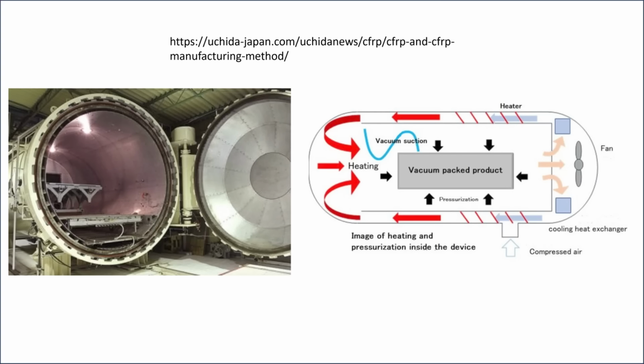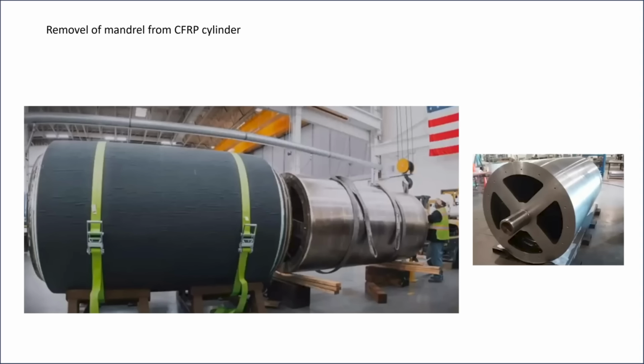After winding, the composite material is cured to harden the resin and lock the fibers in place. The curing process involves heating the mandrel and wound fibers in an oven or autoclave, following a specific temperature and pressure cycle. Once curing is complete and the composite has solidified, the mandrel is removed.